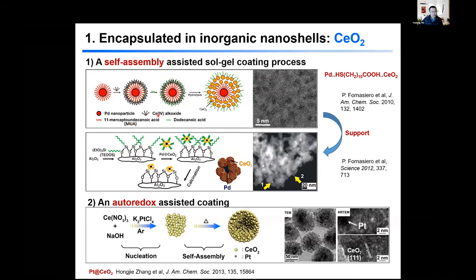And then they introduce this cerium alkoxide based on the adsorption on the surface. And then they stabilize this with additional capping ligand, and then introduce controlled hydrolysis to convert the precursor into cerium oxide. Okay, and the good thing here is that the particles are very small, the coating is very thin, and by modifying the surface of alumina, they can actually introduce these kind of encapsulated nanoparticles onto the support of alumina. And they produce very good catalyst that can be very active for methane oxidation.